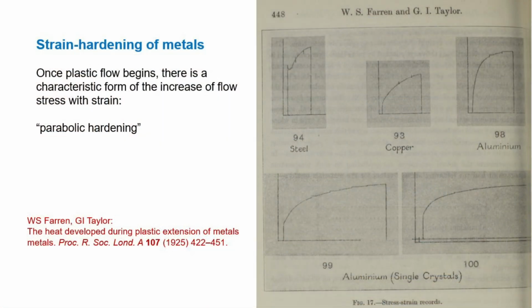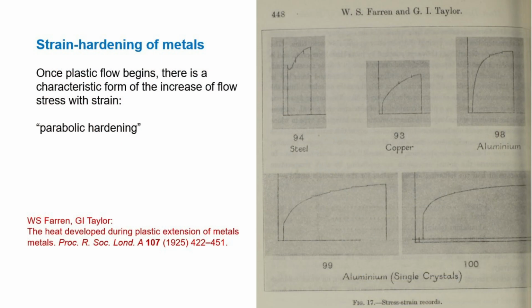In a separate paper, he spotted something else, which is highly important. So here again, we've got one of these, if you like, force extension curves. And the elastic region is now here. The fact that that line is pretty much vertical tells you that the elastic deflection is tiny. But once you go into the plastic regime, the material just keeps going. And if I were to do that with this copper bar in tension, this particular bar would extend its length by 30% before it would finally break. And that's that plastic flow. But as you get it to flow more and more, you have to exert more and more force. And that force has a very characteristic shape, and it shows up again and again. So the force you have to exert increases not linearly with the extension or strain, but roughly as the square root. So it's called parabolic hardening.